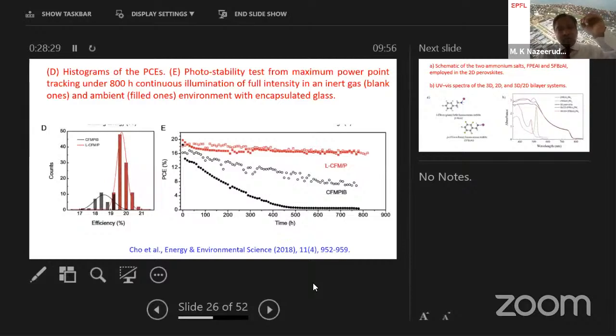There are two types of curves. One is a blank, another is a filled one. The blank one is the stability data measured under argon atmosphere, and then the filled ones are under normal conditions, ambient conditions, encapsulated with the glass.